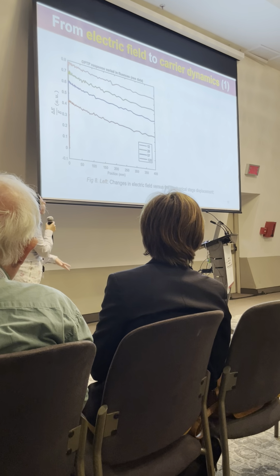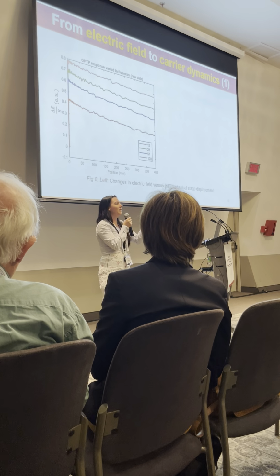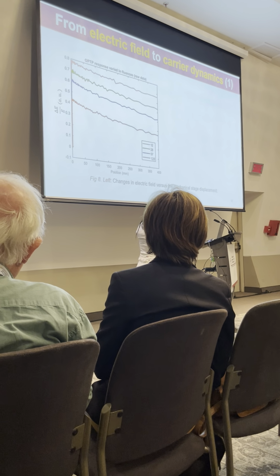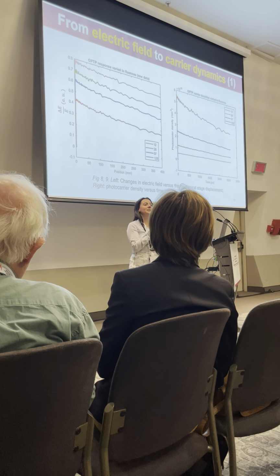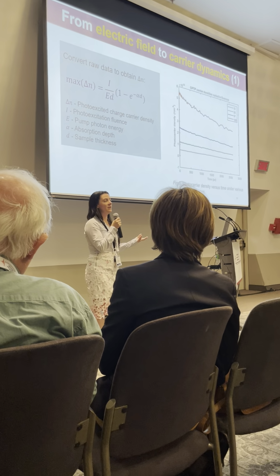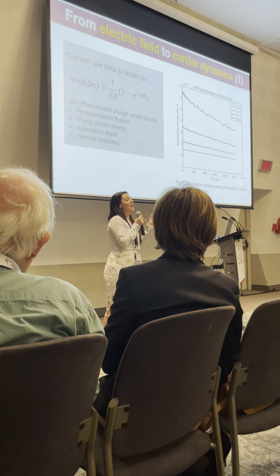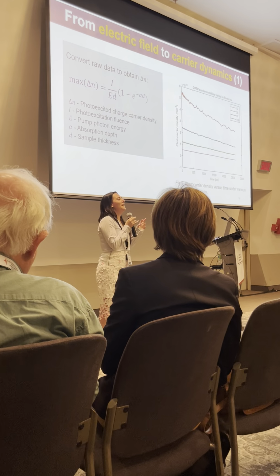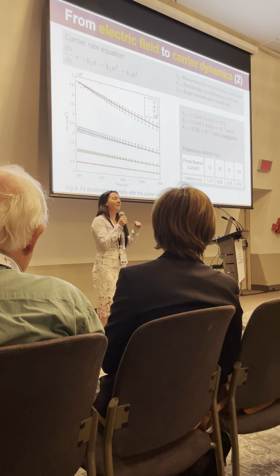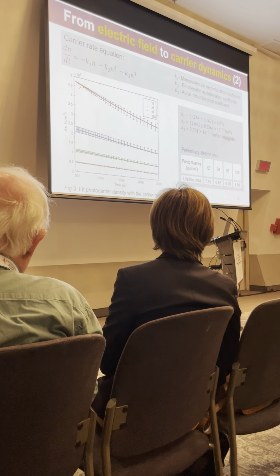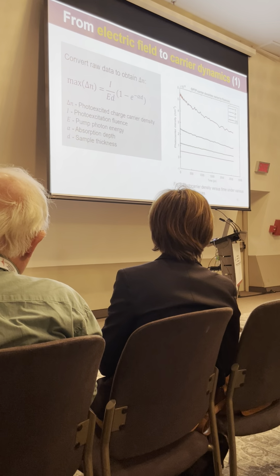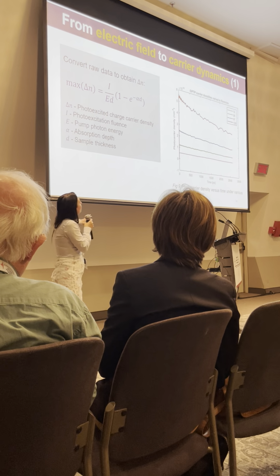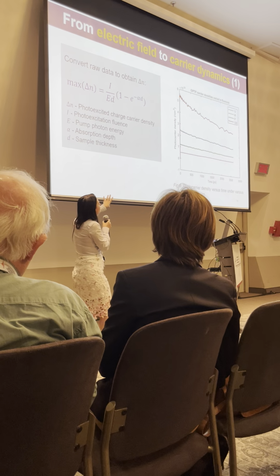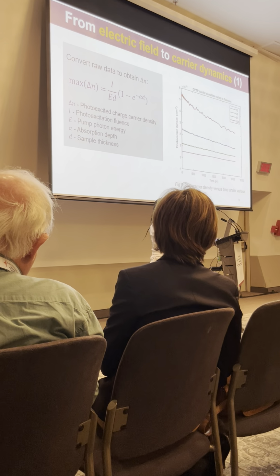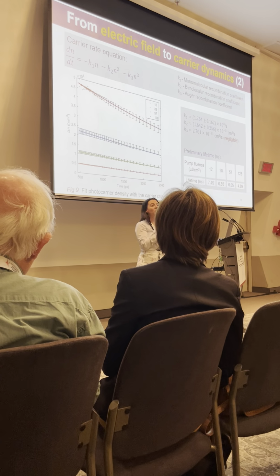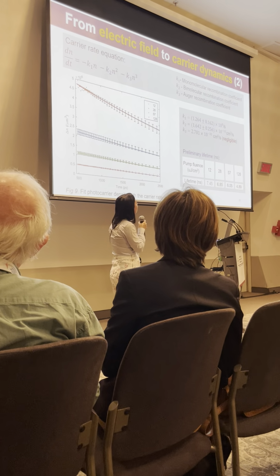So this is our decay data. You'll notice that it looks pretty flat. It's mono-exponential. Already looking at this, mono-exponential decays suggest to us that we have some monomolecular recombination. Automatically, I'm now thinking, is this really monocrystalline? We've got quite a lot of traps possibly, and monomolecular recombination here. So we went back to our collaborators and looked in a little bit more detail, and actually we do have polycrystalline samples. But by using this equation here and taking into account our absorption coefficient, we can convert those decays into carrier densities and start to fit to get those monomolecular, bimolecular, and Auger recombination out.